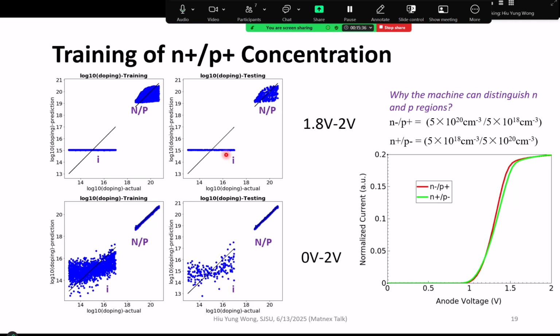Let's ignore this curve because of time. But basically here, the bottom 2 curves show that I can predict the thickness and the doping of the N-type and P-type region very well. Now, as you know, in device physics, the on-state current depends on both the N-type and P-type region resistivity. So here it predicts well. It means that it can even distinguish whether the resistivity is due to the N-type or the P-type. For a human, you cannot do that at all, because basically higher doping is just lower resistivity for N-type and P-type almost at the same time.